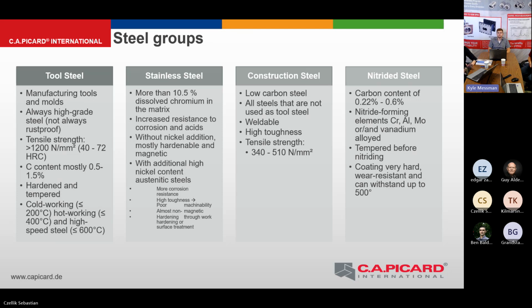They're the type without nickel addition. These are mostly hardenable and magnetic. We are using these steels for most applications because we need the hardness, because at most sites we have wear and corrosion. There are very few applications where we have only corrosion. And then there are steels with a high nickel content.